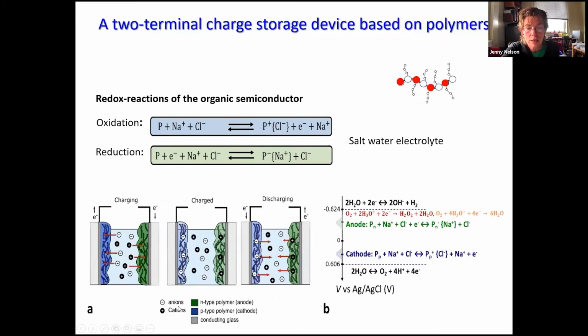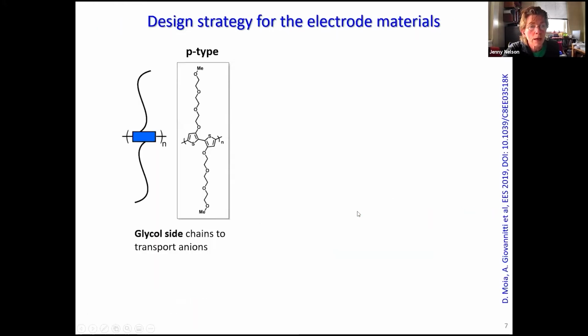And then our idea was to use such a material as the positive and the negative electrode in a two-terminal device, and operate that ideally with a saltwater electrolyte, where on one side you would have a p-type polymer, which would become positively charged and take up ions, chloride ions in this case, from the electrolyte, and on the other side an n-type polymer, which would take up sodium ions, and then when discharged, it would release those and deliver a current. If we're working in an aqueous electrolyte, we need to do those reactions within the electrochemical window of water, so we don't oxidize or reduce water. So that was the plan. And then we decided to work with a series of p-type and n-type polymers.